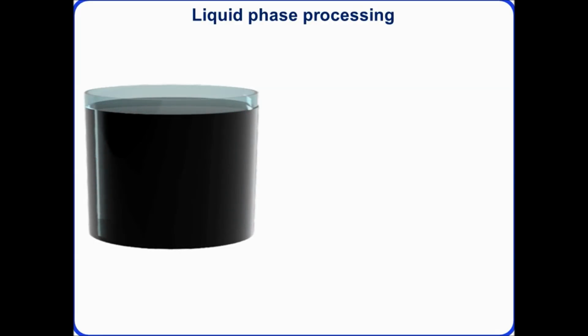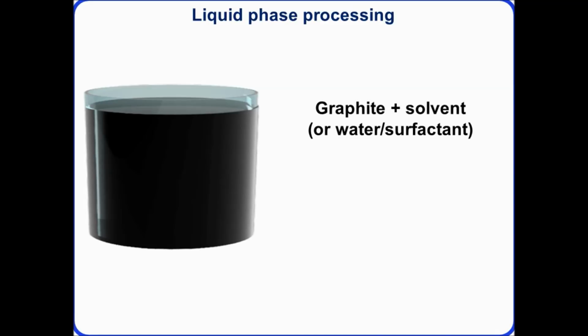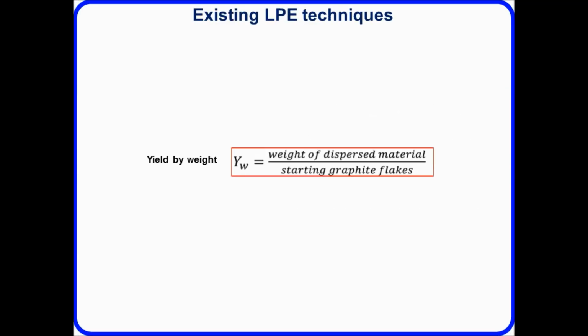So how do we then do this liquid phase exfoliation? We start with the graphite powder. We can take a special solvent, or we can use a water solvent with a surfactant. The surfactant can help stabilize the graphene layers once they are exfoliated. We apply some energy, normally in the form of high shear, and we then have a resulting graphene dispersion. In most cases there is a large proportion of unexfoliated material which we then need to separate after, but I'm not going to go into too much detail on this separation process in this talk today. Most of the existing techniques we can compare by the yield of the process, the weight of what's dispersed divided by the starting mass of graphite flakes.